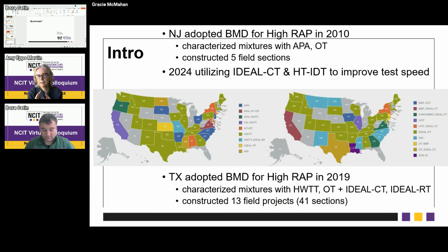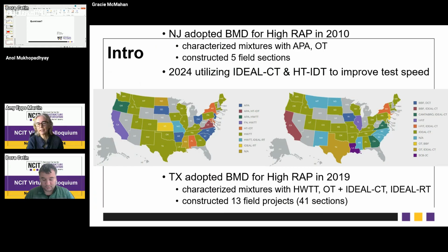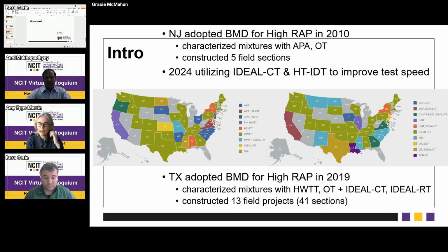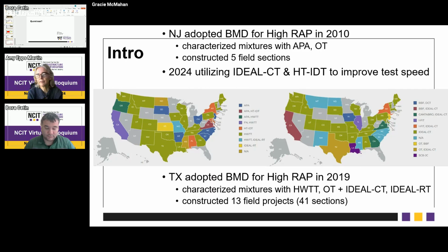So this project is a combination project between New Jersey at Rutgers and TTI in Texas. And each state is doing pretty significantly different things. But just as a background, New Jersey adopted balanced mix design for high RAP in 2010. So that's almost 14 years ago. And they characterize mixtures with repeated loading tests. And I'll show you a repeated loading test, the overlay tester and the asphalt pavement analyzer to look at cracking resistance and rutting resistance.